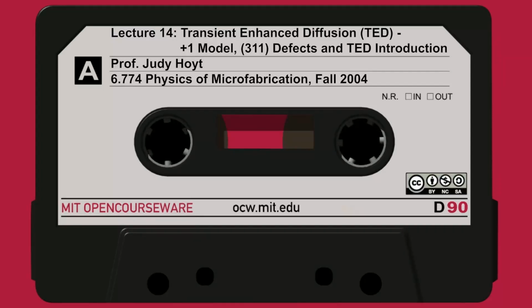And here we have a relatively simple expression for the time constant, the length of time that TED lasts as a function of temperature. It depends exponentially on the temperature, and inside the exponential over kT, I have the binding energy plus EM, the migration energy. So I have a nice little formula for how long TED lasts. And it depends on the dose too, and on Rp.